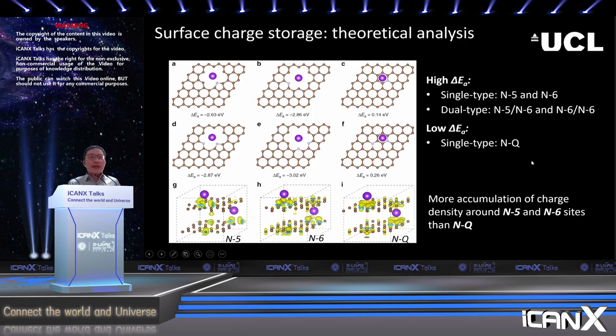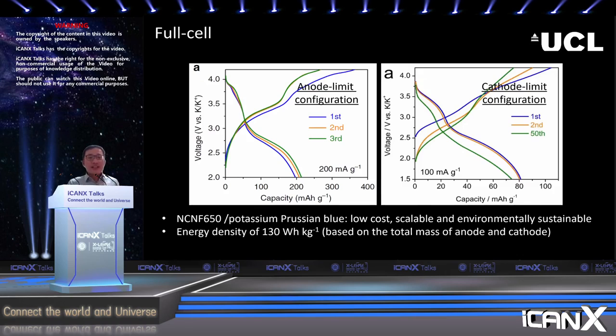Of course, we did a very preliminary demonstration using this material. We paired it up with the potassium Prussian blue, which is also developed by our group in 2017. So we use Prussian blue as the cathode material. We use the 650 degrees material as the anode material. We coupled them up, we made the full cell batteries, and we tested the batteries at two different types of configurations, anode limited and cathode limited configurations. And in both configurations, the batteries showed quite interesting capacity, which is consistent with either anode or cathode performance.